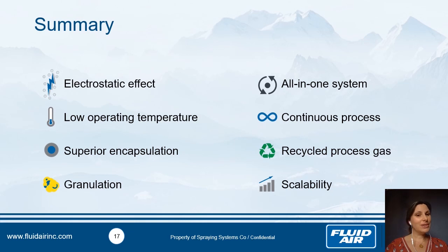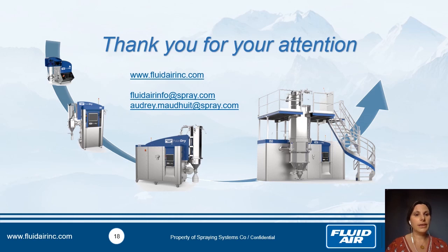Just to conclude, we have an electrostatic effect, and like that we can work at lower temperature. By working with a stratification of the compound, we have a superior microencapsulation. We can also play with electrostatic charge to have granulation. All in one product. It's a continuous process, and we have also recirculation of nitrogen to avoid using too much. And it's very scalable. The model 0.1 that you can see here, and this one is the model 50, and we go up to the model 200.